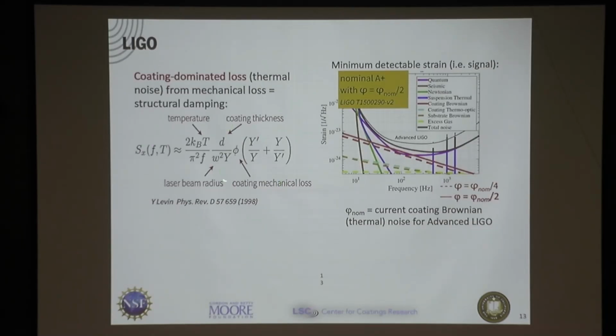And this is captured with this angle, it's captured with this phi. And so what we actually do to measure the mechanical loss is take a very high Q piece of single crystal silicon, I'll show you in a picture in a minute, and you measure its Q. Then you deposit the film on it, and that lowers the Q. It's not as simple as a subtraction, it's a loading process, but more or less, from those two measurements, you measure the ring down before and after depositing the sample, and you can figure out what the Q of your film was.